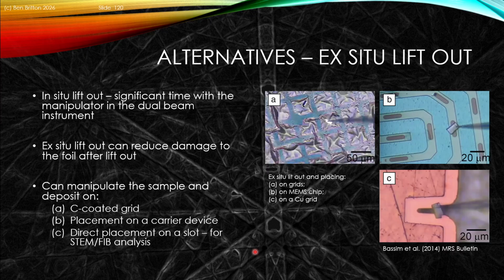If we're moving beyond cryogenic, we don't have to do the full lamellar lift out in the microscope. We could do the liberation of the foil, and then we can use a manipulator needle to enable you to use, for instance, van der Waals forces or similar to lift up and deposit the sample on grids, on MEMS chips, or on copper grids where you could have a hole for electron transparency. The attractive nature of this is that you're not tying up the microscope with that expensive operation, so you can significantly improve throughput of your system. And there are some very sophisticated ex situ lift out hardware now on the market for this. Other aspects is that ex situ lift out can reduce the damage to the foil, and so that can be quite attractive for certain systems. And so here's a series of examples that are presented.